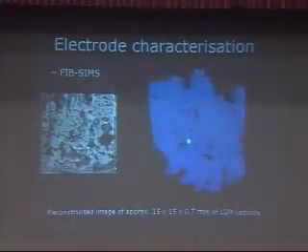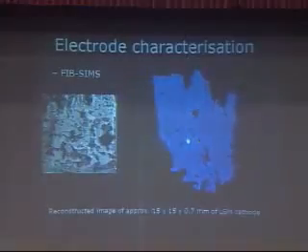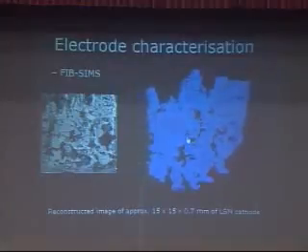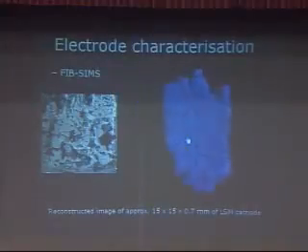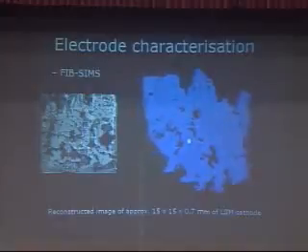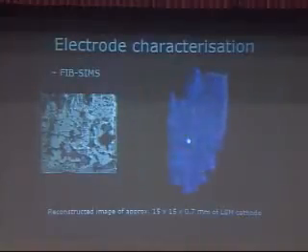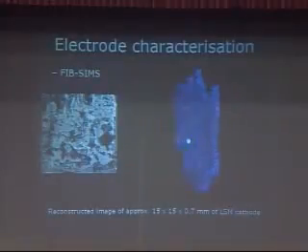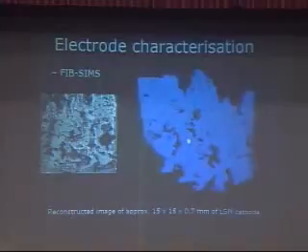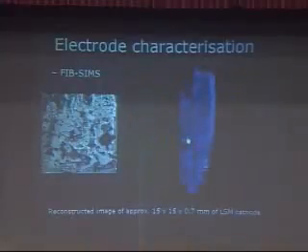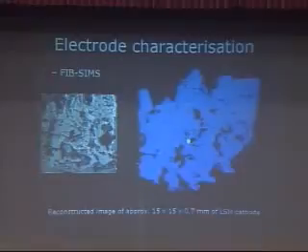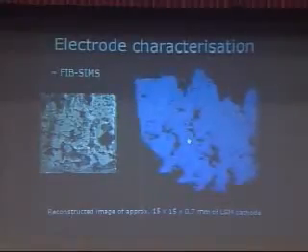On the right is a complete three-dimensional computer representation of that interface, and that has been created by taking the scanning electron microscope image on the left. It's actually a SIMS image, but we won't go into the detail of that. Taking a very thin slice off that, taking the image of the next layer down, and proceeding slice by slice to build up a complete three-dimensional representation of that complex interface between the electrolyte and the electrode.